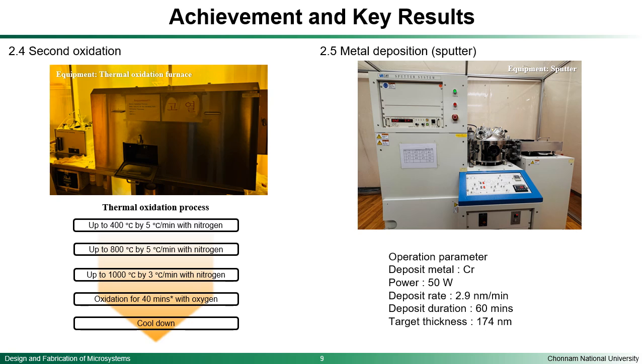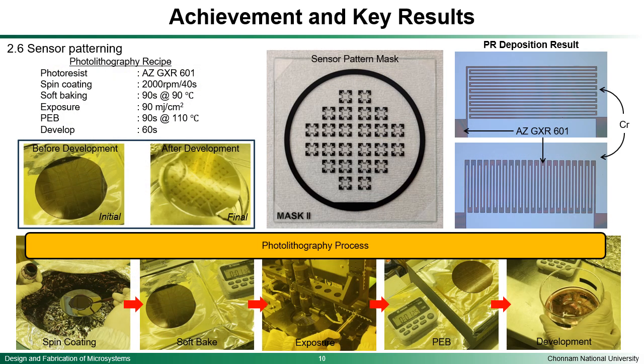that we want to target the deposition of this chromium metal at 174 nanometers, and we utilize the power of 50 watts with a duration of 60 minutes to achieve it, and we can have the deposit rate of 2.9 nanometers per minute. The next one is the sensor patterning.